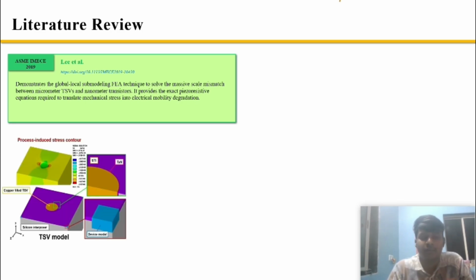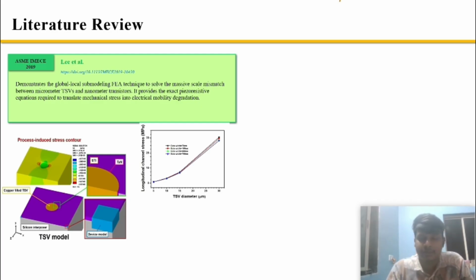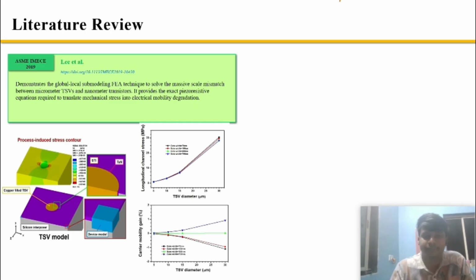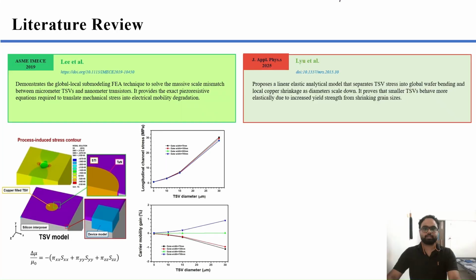So what we can do is create a global-local submodeling. We will find out stresses in a particular area in the global model, and we will remodel the transistor and use those stress values in the local model. As this is the finding, as you can see, the stresses are increasing with the TSV diameter. Also, the carrier mobility gain is decreasing with the TSV diameter for nanoscale transistors. This is the equation we will use primarily from this paper for the carrier mobility loss. So let's move to the second paper.